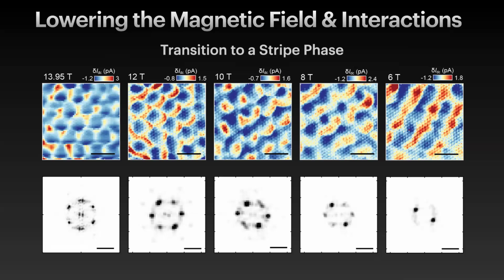So another interesting thing we found was that as you reduce the magnetic field, the same field of view, which reduces the strength of the Coulomb interaction in this problem, you go from a Wigner crystal to a stripe phase. And what's curious, and this stripe phase actually, its orientation can change. This is where we know that the lattice has no importance, and it shows very nice one directional degrees of freedom. And again, its Q vector is that of the Wigner crystal, okay, which is quite interesting.